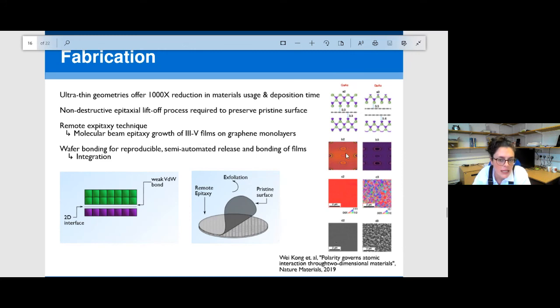And here you have DFT calculations for the potential fluctuation at the surface, and ultimately how that affects what you observe when you try to grow a film, and that you can grow a monocrystalline film where you have a monolayer interface, but if you have a bilayer interface layer, it will be polycrystalline. So it's really extremely sensitive to that separation gap and the need for pristine surfaces.